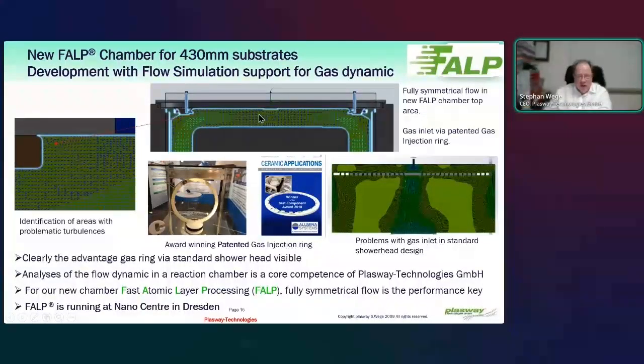First of all, our FALP system is now a new system where we have on the one hand this 430mm ring. This is what you see here. But we made a completely new design of the gas distribution function in the chamber. So we have a very nice laminar flow, and we have symmetric pumping. We put a big turbo pump in the center of the system. So now we have a really uniform, all-over symmetric situation.